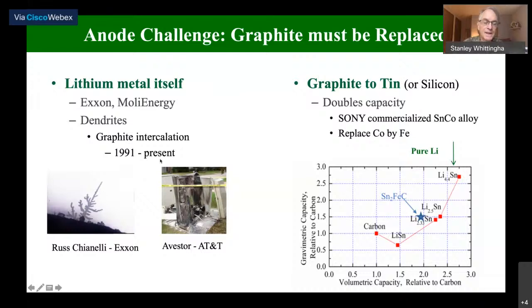So some of these cells were used by AT&T. They were built by Avastor in Canada, and these were in fact all solid state cells. Lithium anode, a polyethylene oxide electrolyte, and I think a vanadium oxide cathode. And a number of these caught fire within just a few months of installation. And that was the end of lithium metal in most batteries until the present day when there's a few applications coming up.